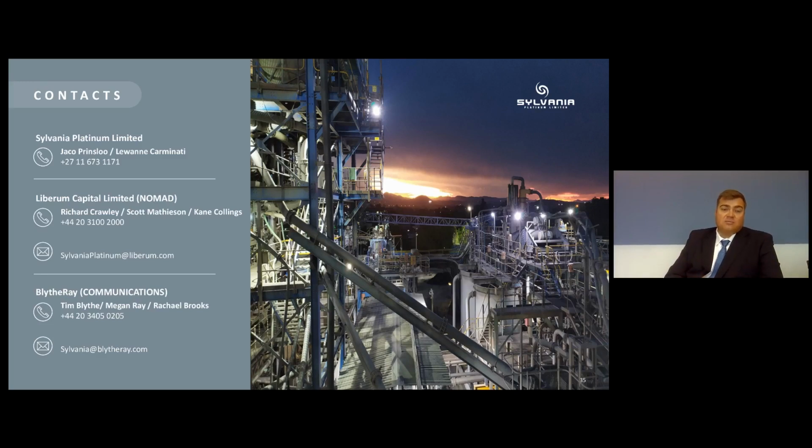One benefit from it. Probably on the downside is there's no chrome revenue from any chrome produced. But on the positive side, one of the key impacts with smelters being able to treat your concentrate from these projects is the chrome content. On our current operations, chrome is viewed very negatively in platinum concentrate by smelters, whereas in these projects there is no chrome. So that should help us in terms of the commercial marketing of the concentrates.